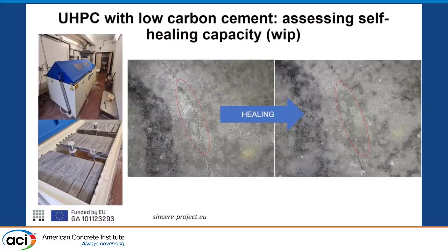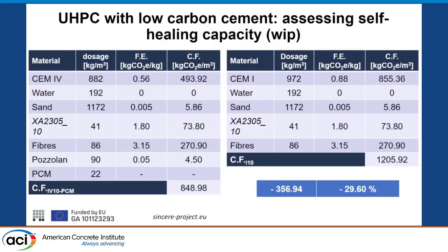Now, because we go with these blended cements, we are in the process of verifying the self-healing capacity of this mix in a specific environment. This is a saline fog chamber that we have in our lab, so we wanted to test how it behaves in an environment close to the sea. We put the specimens here, and you can see there was a crack here, and after 28 days, the crack here is completely healed. There are still some parts that are going to be opened, but we keep monitoring that.